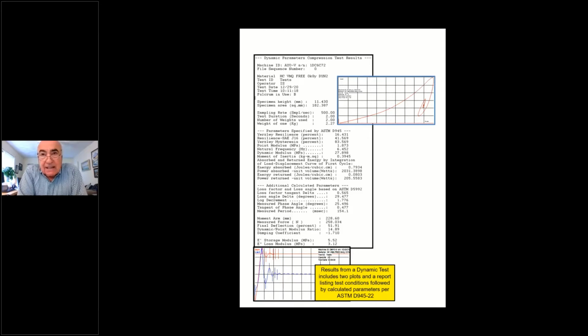And then it has to calculate natural frequency throughout that scan. In our case, our natural frequency comes out in 3 to 5 seconds, and that's what we are looking at. So with this 5992 test method, we do calculate the loss factor tangent delta and the angle delta. But on the other hand, we do log decrement, and we also measure phase angle. That's the difference between the two plots we have down below, which is the load and displacement against time.